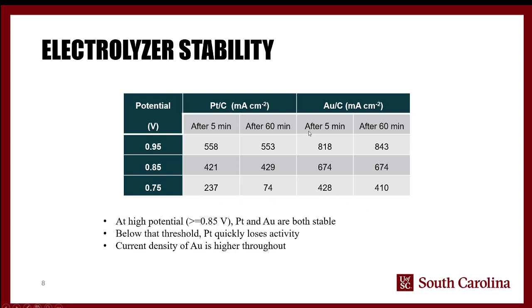But more importantly, gold maintains its stability at these voltages, whereas platinum, once you go below 0.85, drops off very quickly. This drop off is recorded after an hour, but in practice it takes something more like 5 to 10 minutes to see the drop off happen. And you'll see an immediate loss of activity. You can sometimes get it to recover if you reapply a high potential, but as soon as you go back to the lower potential, you'll see the drop off happen again.